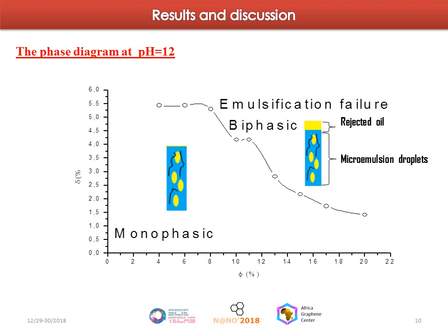To summarize the observations: for low charge densities, the solutions are monophasic and transparent over the whole range of microemulsion concentration, whereas they are biphasic at higher charge densities. Upon increasing, one again observes a phase separation between a viscous phase and a liquid phase, and also for low drop concentration the phase separation appears for larger charge density.